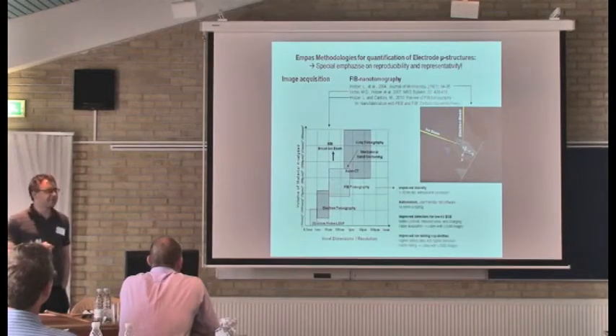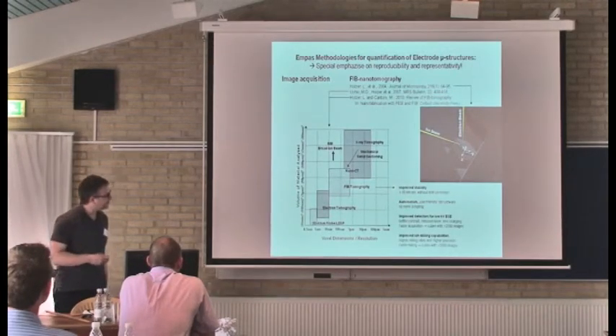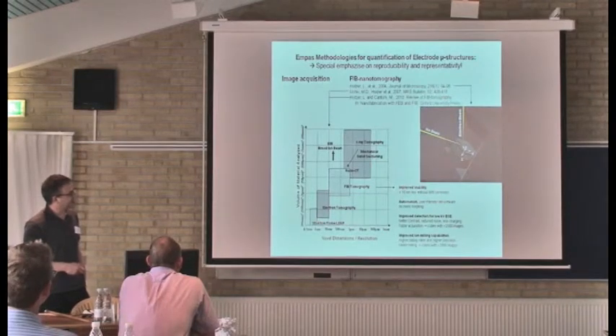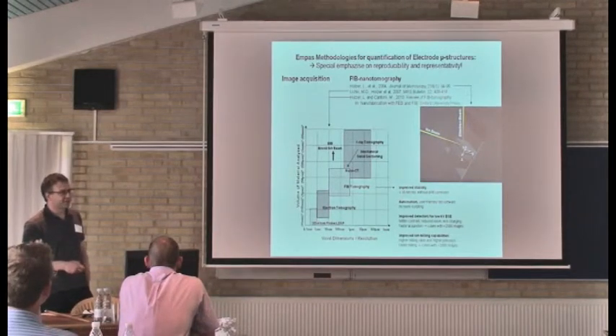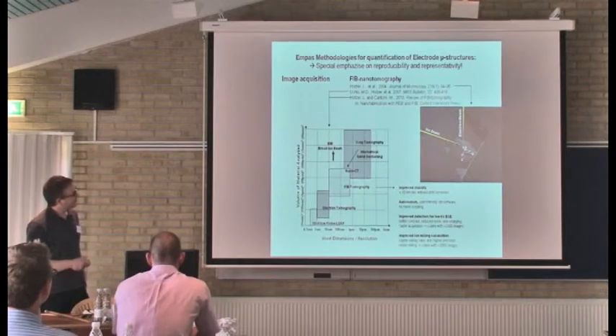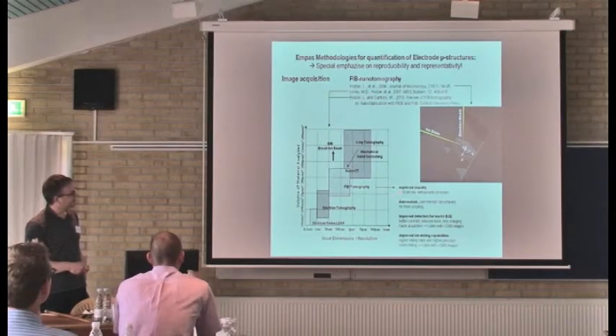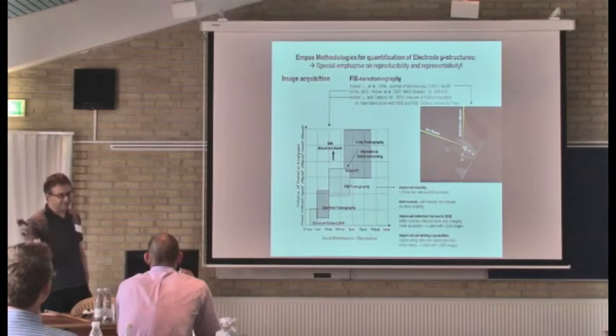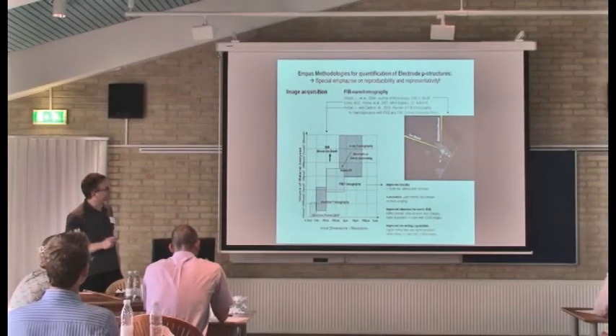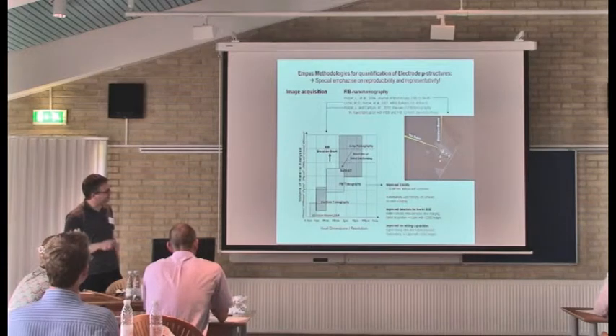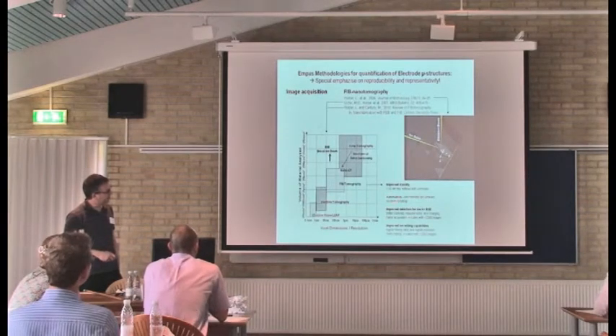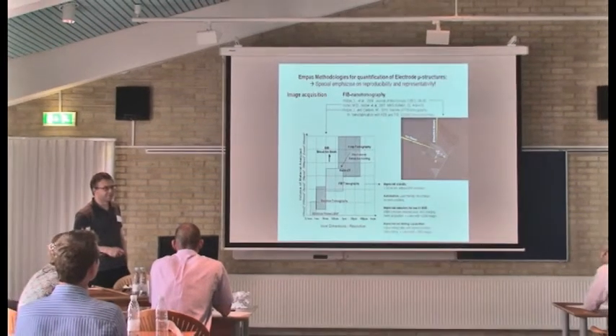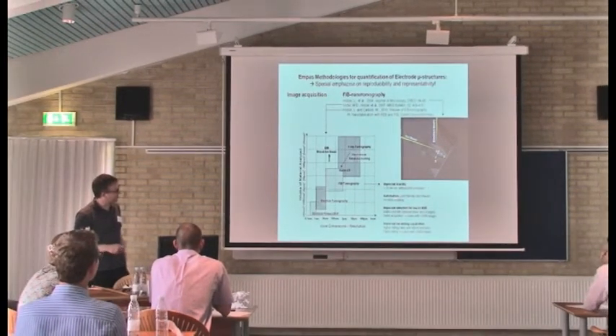When I'm looking back at what has changed with FIB tomography, one thing today is certainly improved stability. A couple of years ago, when you wanted to do imaging at 10 nanometer resolution, you immediately ran into problems with drift, so we had to implement drift correction. Nowadays, this is all really automatic standard solutions.